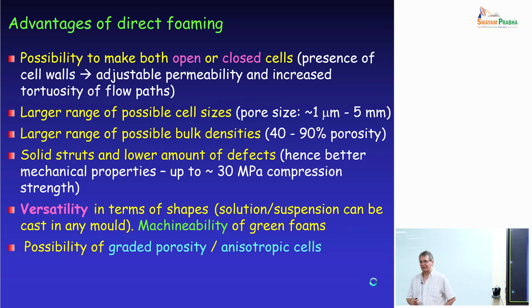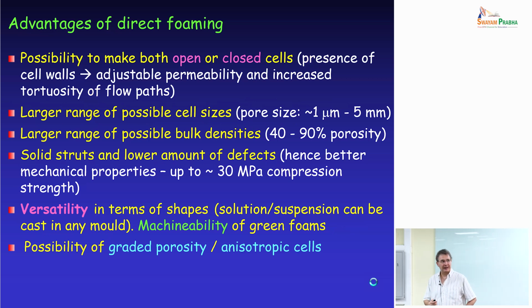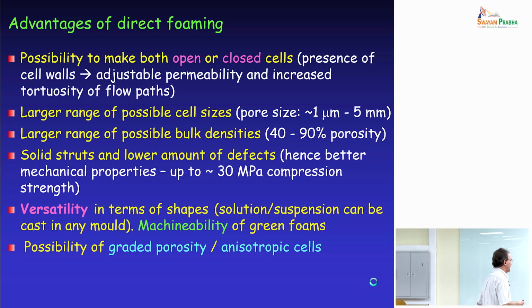So there are some advantages with direct foaming. You can obtain both open and closed cells. You have a wide range of possible cell sizes. You have a much wider range in terms of the bulk densities, the amount of porosity that you have. The solid struts have a lower amount of defects, certainly with respect to the reticulated foams.